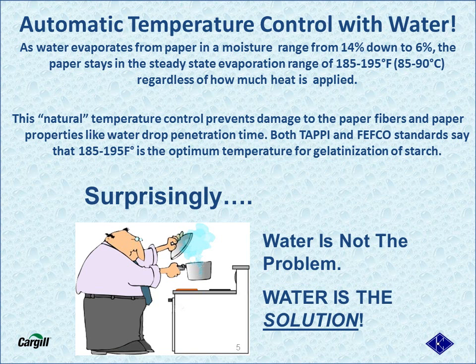Isothermal corrugating essentially provides automatic temperature control of the process by using water at its evaporating temperature. This natural temperature control will prevent damage to the paper fibers and properties like water drop penetration time. Both TAPPI and FEFCO standards say that 185 to 195 degrees Fahrenheit is the optimum temperature for the gelatinization of starch. This is the temperature that we maintain by applying a thin film of water to the medium and liners. Surprisingly, adding controllable moisture is the solution and not the problem.